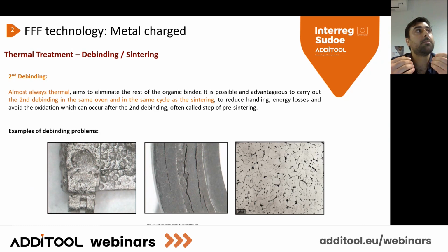However, you can also have a little bit of contamination during the first debinding or second debinding and the sintering. You have a lot of polymer that is vaporized, and you can have contamination in your oven. So it's important to note also.